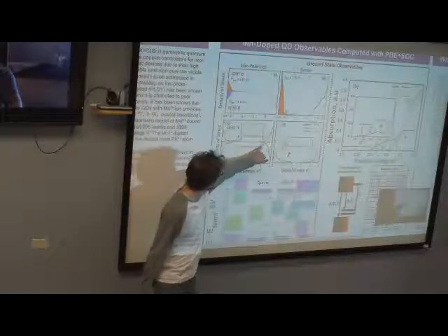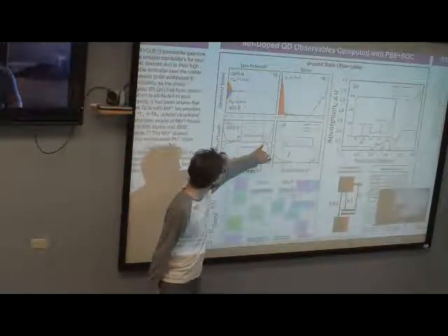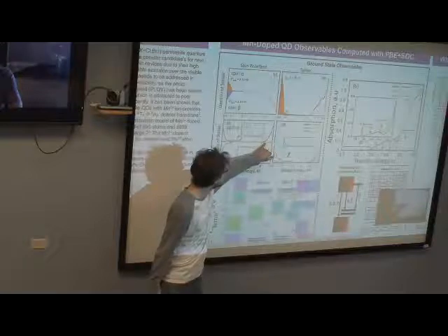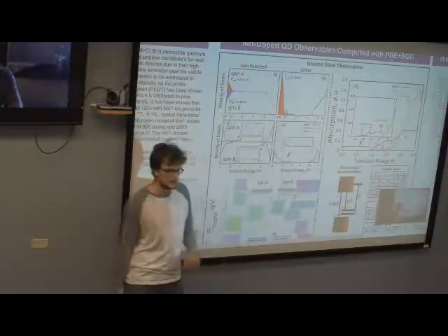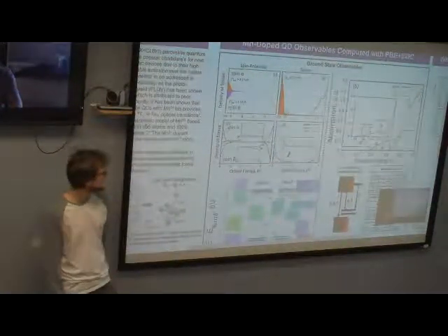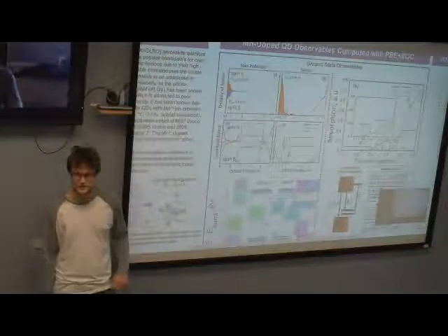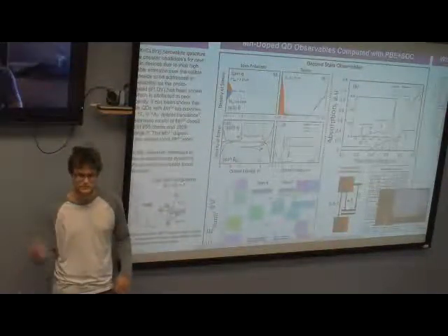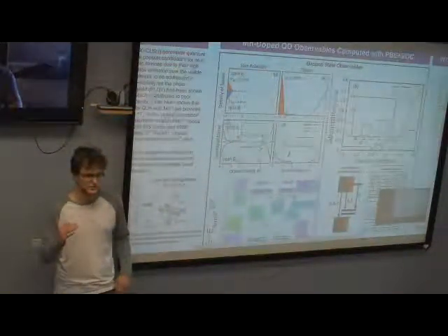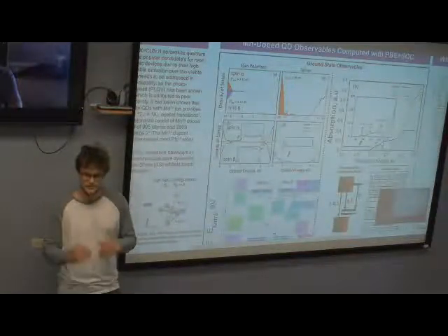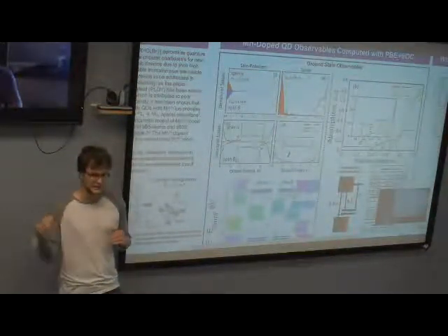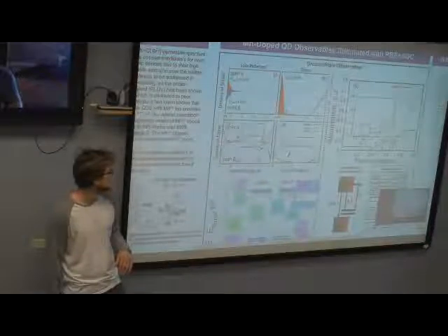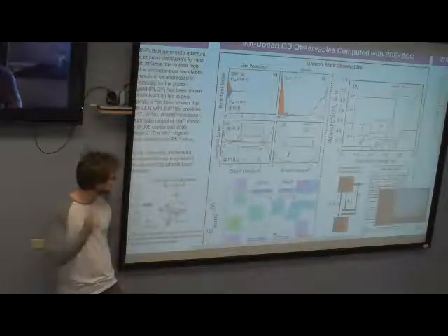And we do see that in the conduction band there are some Mn D states hanging around just around the conduction band edge, which is a good sign, because if you're trying to get photoluminescence for the materials, you want those D states to be near the band edge so that after non-radiative relaxation, no electron occupies there.